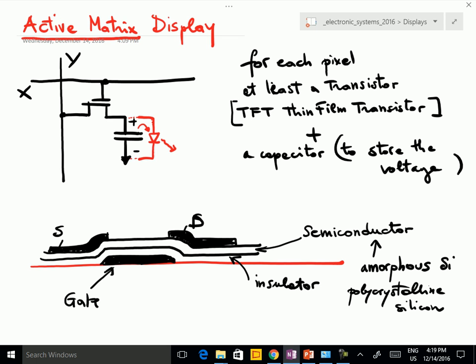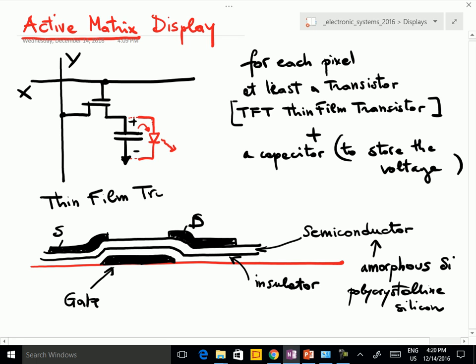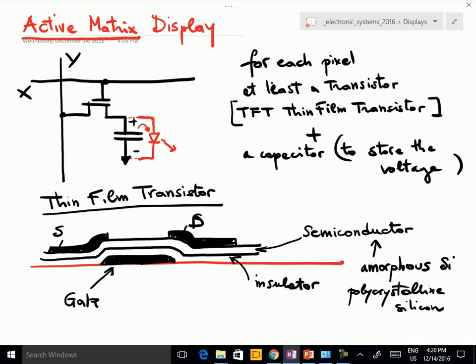All these different layers are fabricated with a technology similar to printing, which means these materials are not crystalline. The semiconductor is typically amorphous silicon — a non-crystalline type of silicon with very poor properties, not usable for a microprocessor, but good enough for making a display because it just has to activate a pixel — or polycrystalline silicon. The main properties this technology must have are that it must be cheap (used on large areas) and processable at low temperature, typically no more than 200 degrees.